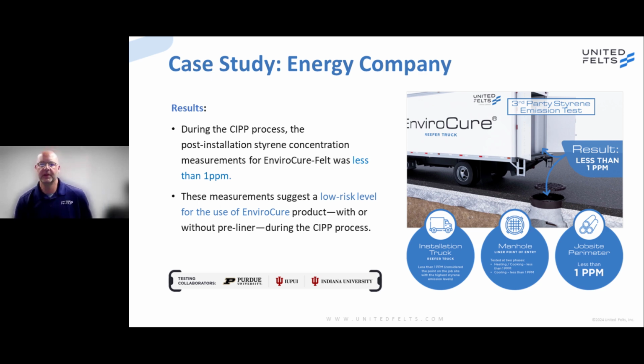So during the CIPP process, and within all the measuring devices, the styrene content was always found to be less than 1 part per million. So as the reefer truck doors were open, less than 1 part per million styrene was found. At the manholes, at the liner entry points and exit points, during heating and cooking, less than 1 part per